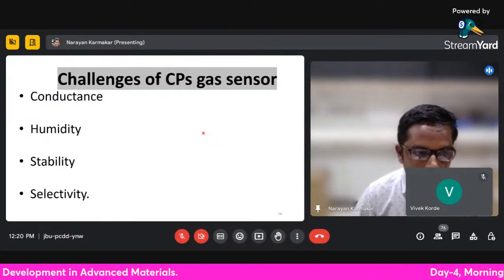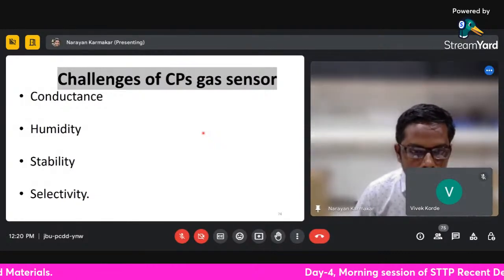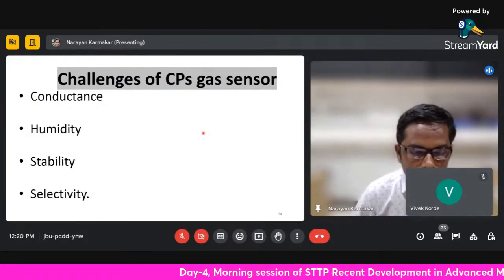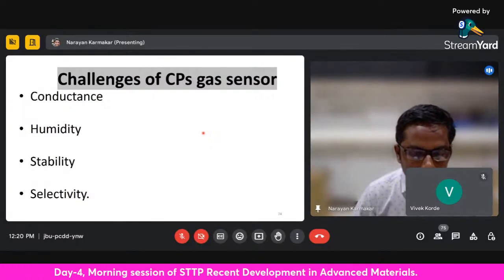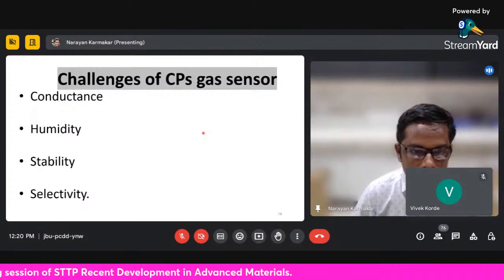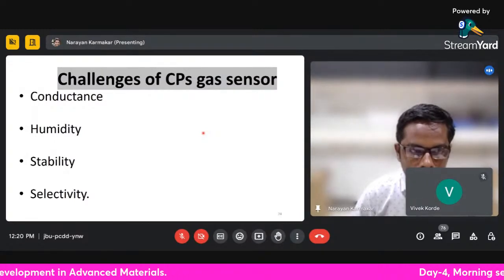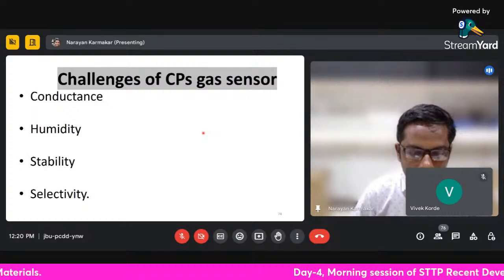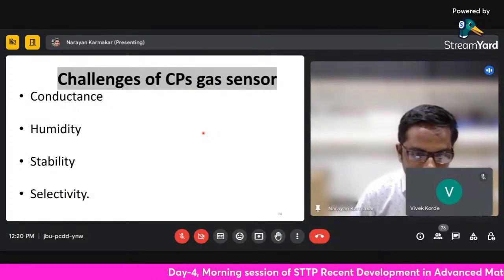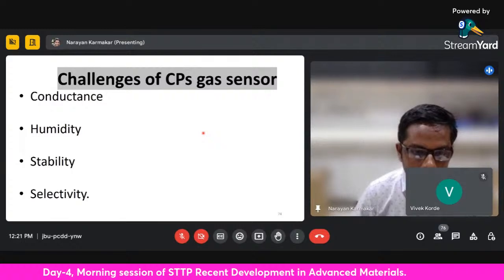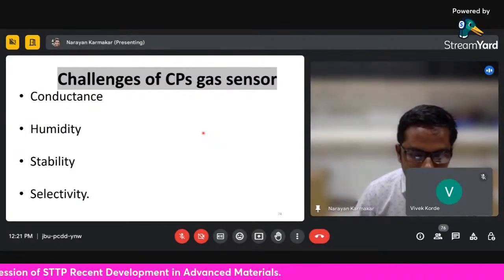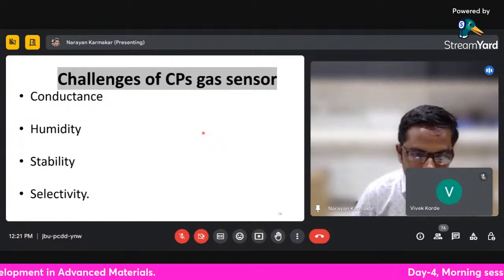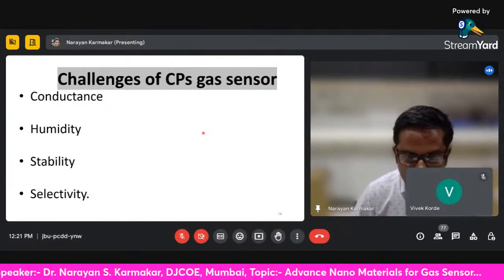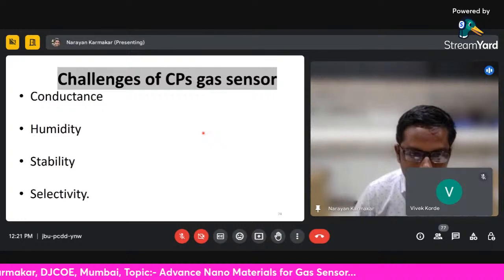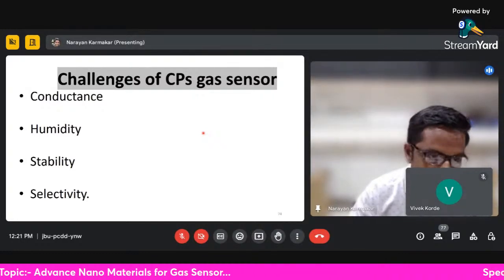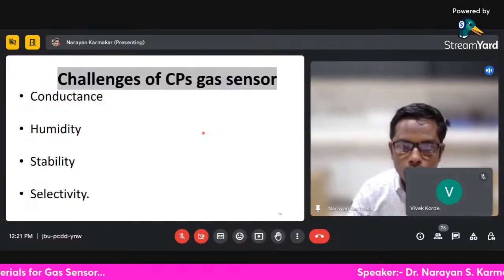This selectivity issue can mainly be solved by using multi-array sensors. What you do is take a substrate and mount various sensors on it: one sensitive to NO2, another sensitive to ammonia, another sensitive to H2S. So we have a multi-array of sensors mounted on a specific substrate, and we use the different sensor arrays coupled with an algorithm and study the behavior, and you can differentiate between the different gases. So this is the solution for the selectivity of these gases.